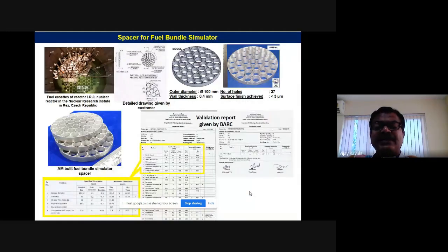And then, like I was mentioning, the fuel pins in a nuclear reactor. How do they hold them? They use a fuel bundle spacer plate, which is kind of a ring, so that each fuel pin goes in each hole. But making it by conventional machining needs so much drilling and machining, with only a 1 mm gap maintained between the plates. The wall thickness is only around 0.4 mm. So it's a very, very difficult thing to do by conventional methods.